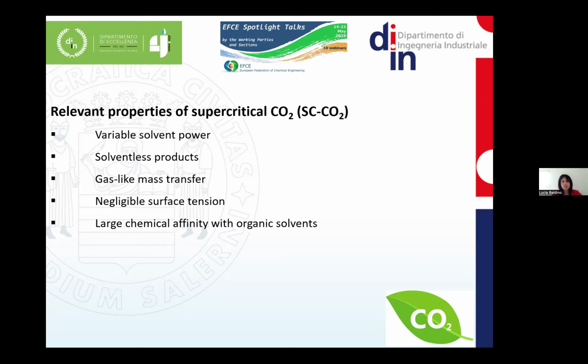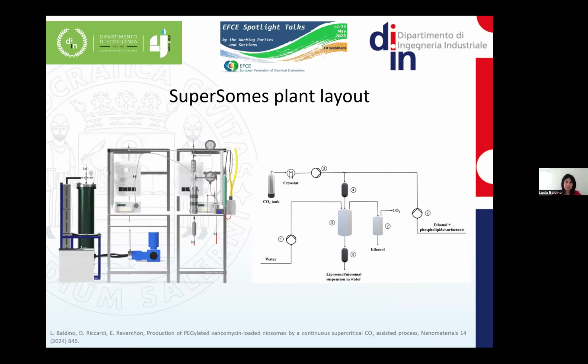Negligible surface tension. This property is important when we want to produce nanostructured material. We can avoid the collapse of this structure at nanoscale. And large chemical affinity with organic solvents. Therefore, CO2 is a good anti-solvent.